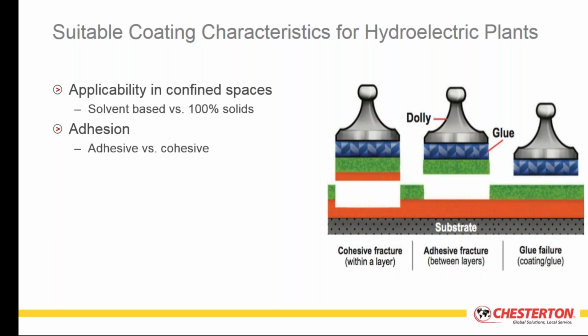And that's what you want to see. So the left-hand image is the mode of failure that is desirable in a coating system. It means that the coating's adhesive properties are greater than its cohesive properties. So even if the coating does shear somewhat, there is always a protective layer left on the surface which will provide protection of the base metal.